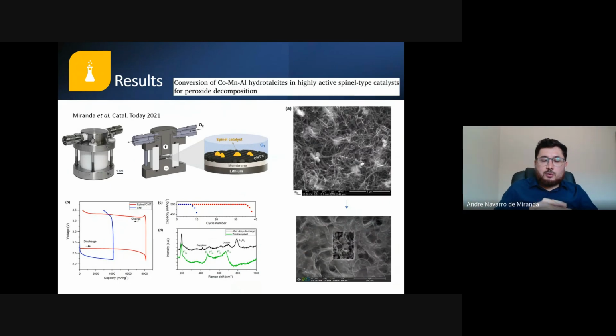Sure, thank you for your question. It's a good point. Actually, we have studied the catalyst over cycles, and we saw that it doesn't decompose. It doesn't break, it doesn't change phase. What happened here is more about the morphology of the cathode. As you can see here, the cathode has a thick layer of lithium peroxide, so we cannot access the cobalt phase here. On the surface, we can just see the DMSO, some residue from the tests, and mostly lithium peroxide. So it's more about the morphology of the cathode after discharge and not about the decomposition of the catalyst. But it's a nice insight. Thank you for the question.